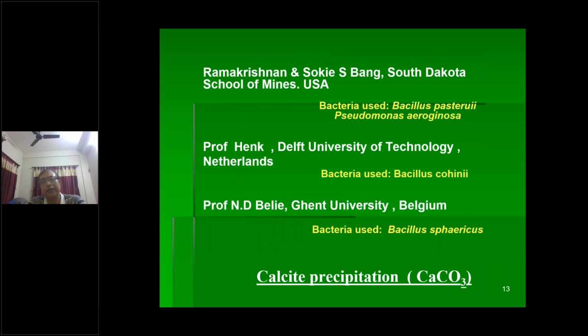In fact, researchers have used different bacteria, such as Ramakrishnan and Sokie Bang's group at the South Dakota School of Mines. They started very early. They used Bacillus pasteurii and Pseudomonas aeruginosa. Professor Jonkers from Delft University of Technology, Netherlands, used Bacillus cohnii. Professor N. De Belie, Ghent University, Belgium, used Bacillus sphaericus. The character of these bacteria within the concrete is that they produce calcite precipitation, that is, calcium carbonate. These precipitations fill the pores within the concrete, and that is why there is an improvement in strength.